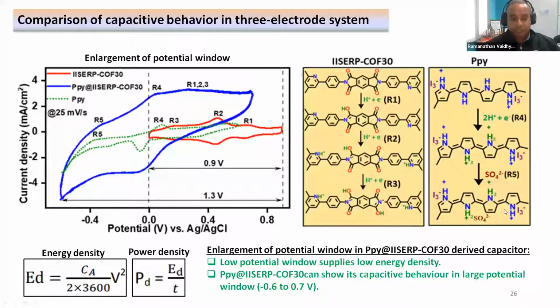from the electrolyte medium. This is very important because if you look at the energy density equation, you have charge capacity multiplied by the voltage window, which directly tells you the energy density of your charge storage. You want a very high value here, which means if you have a high charge capacity, then the material is likely to give you high energy density, and power density is nothing but a function of time. So one important thing is we want to expand the potential window for this material beyond 0.8 volts, which means when the voltage goes much higher, your energy density can be enhanced.